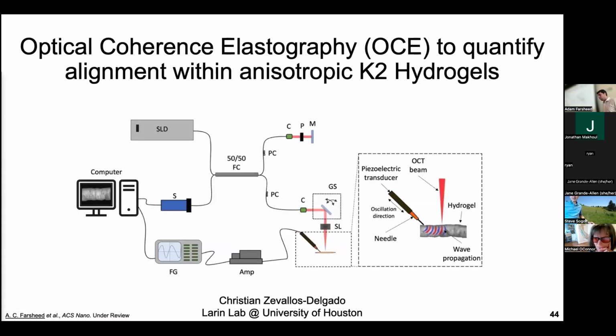And to quantitatively assess this behavior, we turn to a technique called optical coherence elastography, which here's a full schematic of the system, but I want to draw your attention to the far right part. But before I get into that, why are we using this technique as opposed to just rheology like I showed in the first aim? Well, rheology is not designed for anisotropic materials. It's designed for materials that act the same in every direction. And because we have an anisotropic noodle system, what you would usually turn to is some sort of tensile testing or some sort of poking testing. But our weakest noodles aren't really strong enough to carry out any of those tests.